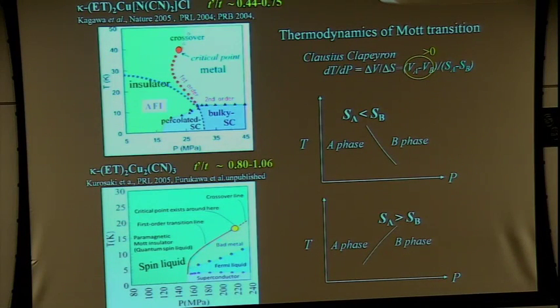Okay, let's take a look at the phase diagrams of the two materials. One is the antiferromagnetic Mott insulator. The other one is the spin-liquid Mott insulator. So you see a very contrasting phase boundary, which shows a negative slope in the antiferromagnetic case and a positive slope in the spin-liquid case. So even in the antiferromagnetic case, at high temperatures, the slope is positive. So, positive slope means that the entropy of the A phase is greater than the B phase. It's very reasonable because in the spin liquid materials, the spins are very alive. It's vital, so the spin entropy is very high compared with the Fermi degenerate metal, the Fermi liquid.